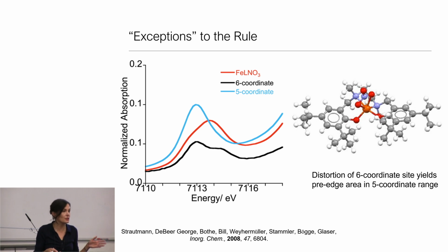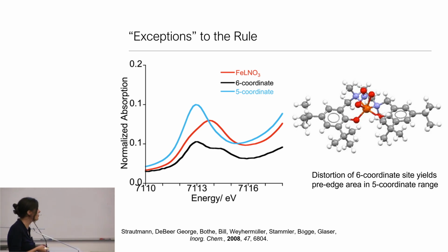And this is exactly the reason why we want to use as many spectroscopic methods as possible. And just to point out, I see some of you squinting at these edges. We generally have to fit a background and then integrate the area. So that's how we're typically comparing these areas.